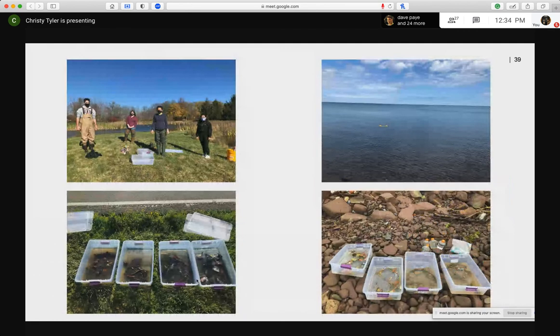This shows some of the students working on our team, well masked and socially distant. And this is at the JLAP pond, and this is Lake Ontario. And then these are the samples collected after just 1 month in the ponds. So you can see this really big difference. This is JLAP. The plastics are really fouled. The ones on the bottom, it's very anoxic. Whereas in Lake Ontario, the ones from the surface are moderately fouled, but the ones on the bottom are fouled much more. There's actually a lot of algal growth that we got on the plastics from the bottom of Lake Ontario.